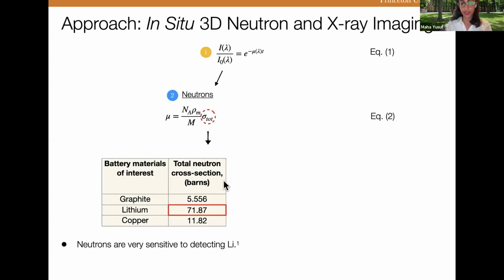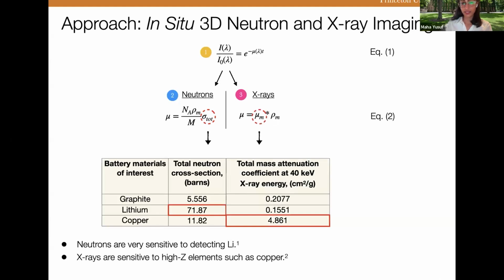Now, let's look at this part of the table. We can see that we have graphite, copper is a metal, and lithium, which is what we want to investigate. You can see that sigma total for lithium is very high, which means neutrons are very sensitive to detecting low Z materials like lithium. Now, if you look on the right side of the equations, you can see this mu for X-rays is directly proportional to mu m, which is the mass attenuation coefficient. Now, this mass attenuation coefficient for copper is very high, which means X-rays are very sensitive to detecting high Z materials such as copper. Thus, the idea is to use the sensitivity of neutrons towards low Z materials like lithium and X-rays towards high Z materials such as copper to identify both the low Z and high Z materials in a battery in situ in 3D without opening it.